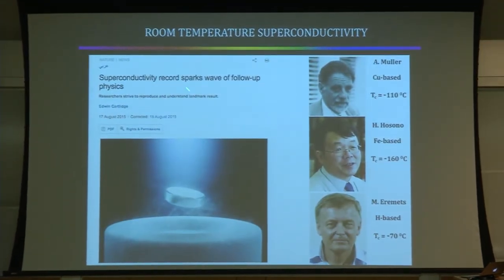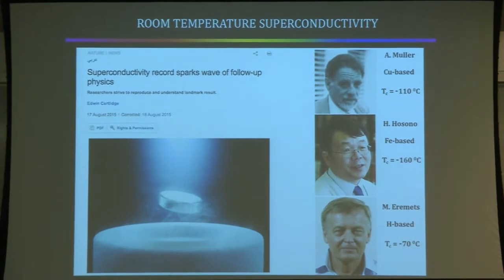Okay, so we're interested in high temperature. We're interested in room temperature superconductivity, and you know how to get there. We have three examples of how to get there now. We have copper-based high-temperature superconductivity. It's about minus 110 degrees centigrade. Iron-based, maximum now is somewhere near minus 160 degrees. And hydrogen-based, maximum is minus 70 degrees.